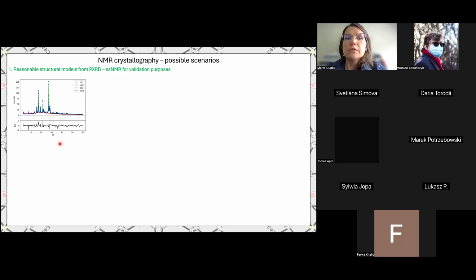And then for this model, you can calculate NMR parameters in DFT codes. That allows you to run calculations under periodic boundary conditions, so for a unit cell of a crystal, and then you can compare those calculated theoretical values of the chemical shieldings with your experimental chemical shift values. And here, proton MAS experiments are the most informative, because protons are the most sensitive to any local changes in the crystals.